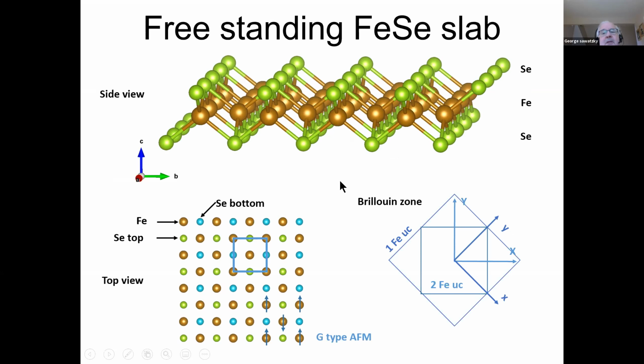And we know from the work of Ole Krogh-Andersen that whether you have a magnetic moment on iron or not very strongly influences the selenium to iron plane distance, okay? The distance that you generally get from density functional theory is much smaller than it is experimentally. But as soon as you put in magnetism, then that distance becomes much closer to the experimental distance that is measured. Okay, so magnetism has a very strong coupling to the lattice, and this sort of matches with what we just heard from Bard about the 1111 material and other iron pnictide-like systems.